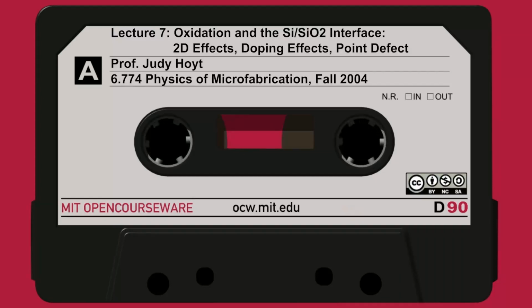Here on slide 37, it's just a simulation of this type of effect. What we have on the left-hand side is local oxidation, taking place at 800 degrees for 30 minutes, and you're seeing you get a little thicker oxide. You're going to get a 5 times thicker oxide growing in this heavily doped region. So this region over here on the right is heavily phosphorus doped. So it was ion implanted prior to oxidation. So you need to take this into account.